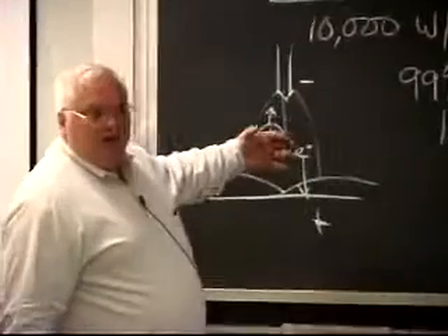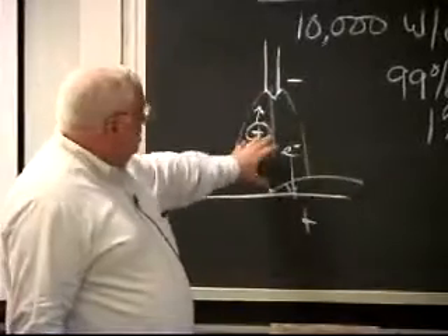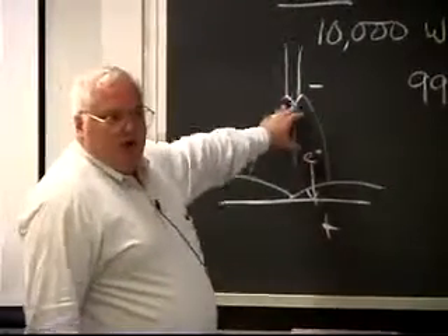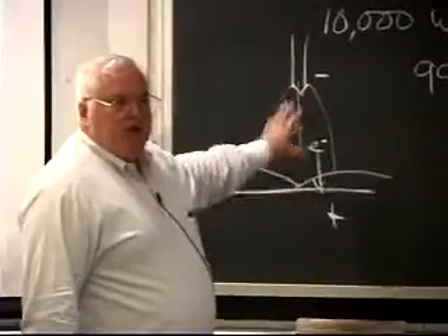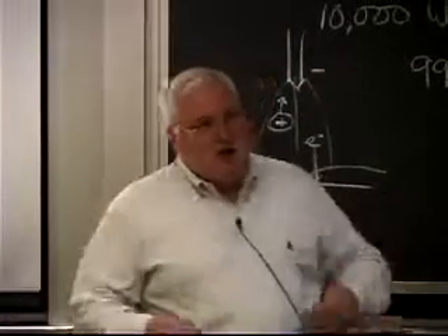However, once this one starts deviating, it's because the argon 2 plus is coming up, and eventually that one goes down and the argon 3 plus comes up. You'll never see argon 2 plus and 3 plus in a welding plasma. In fact, a welding plasma is typically about 5% ionized. You can go through the mobility of these electrons: I've got a plasma of this diameter in argon, plug in the mobility, and say I'm going to have 100 amps or 200 amps. How many electrons do I need with that mobility to carry the current? To carry 100 or 200 or even 1,000 amps, you only need 5 to 20% ionized in that plasma. So the plasma temperature is naturally controlled by the fact that the system wants to generate enough electrons to carry the current.